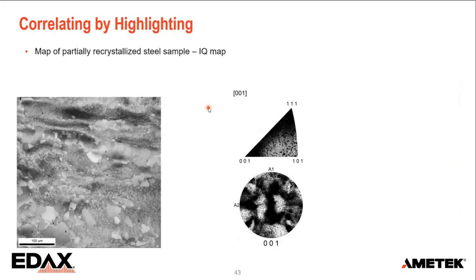Here I have a partially recrystallized steel again, and here I have my pole figures and inverse pole figure. And you can see here on the lower right in this IPF, some black dots. These are actually the points that belong to the recrystallized grains. Those have very sharp, discrete orientations, and you can recognize those dots here as well. But the deformed grains are so bent that the clusters of points belonging to those grains just cover a very large part of the pole figures.